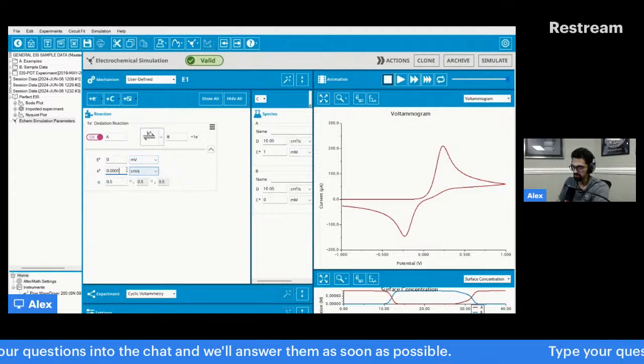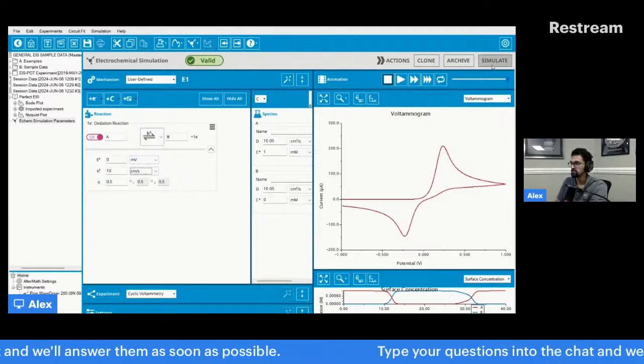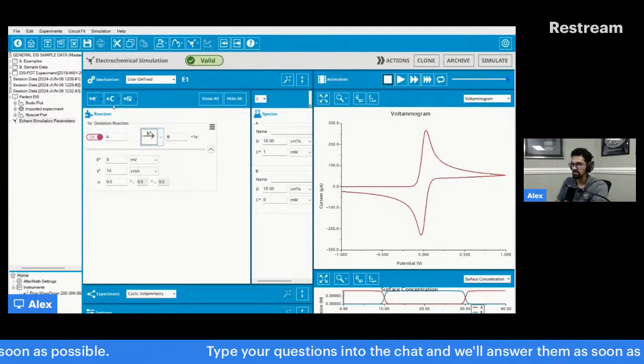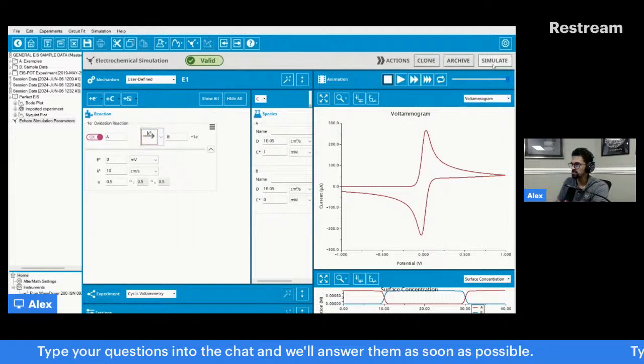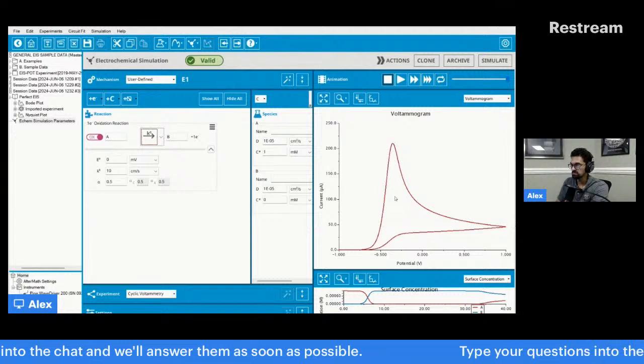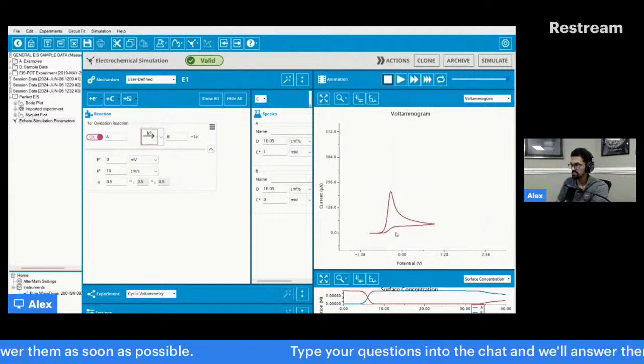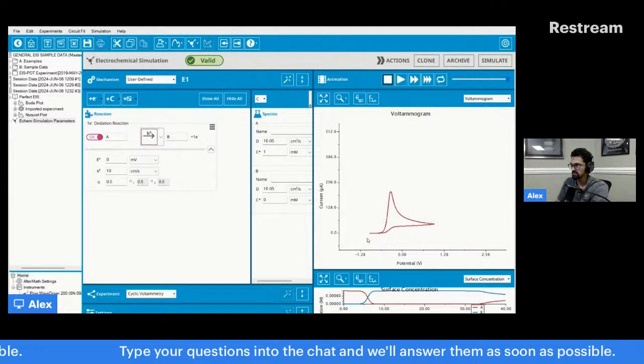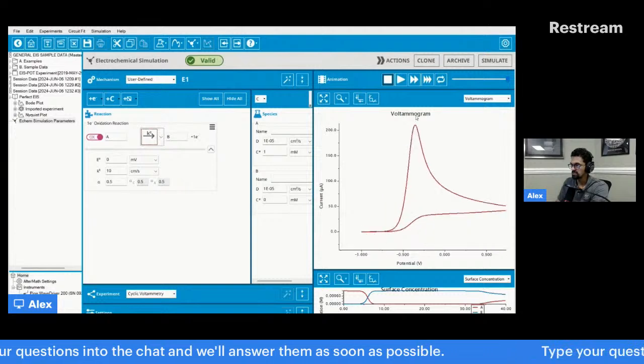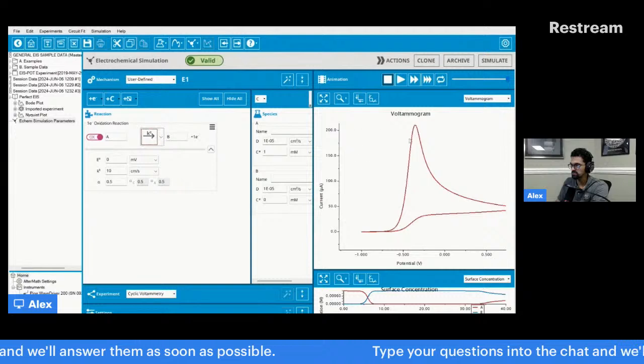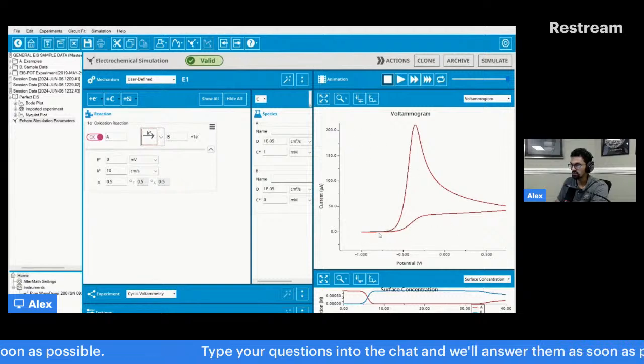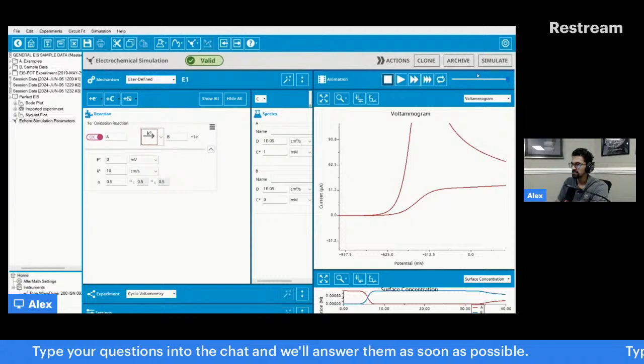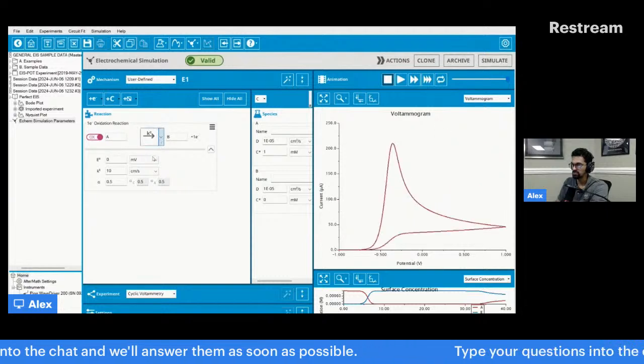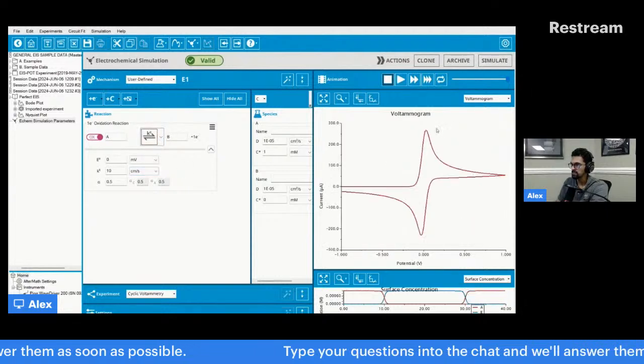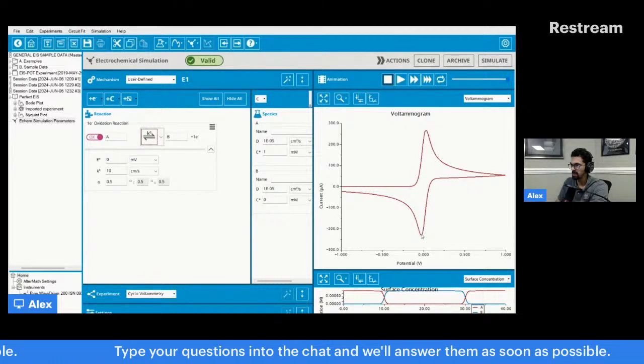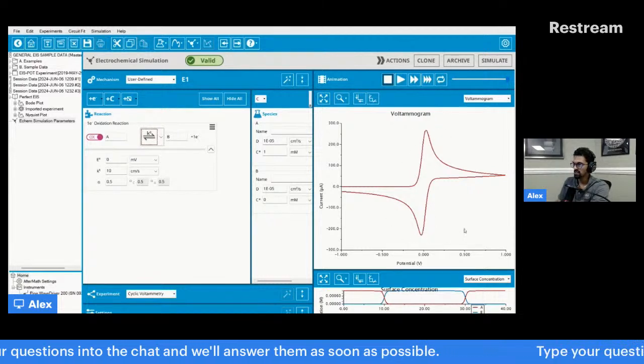Well, right now, I've simulated it in such a way. Oh, there's one more thing. Let me go back to this fully reversible system. I can change it to just be completely irreversible. And when I do that, you only get this. And if I zoom out, you'll notice there's nothing that'll show up on the reverse side. So it starts at minus 1 volt. It scans. It's the same magnitude of current, 200, but there's nothing on the return wave. So I can zoom in. Nothing on the return wave. So that's when it's purely irreversible. If I go back here, simulate, still get this high 200 microamps, and then it goes back to less than 200 microamps on the reduction.